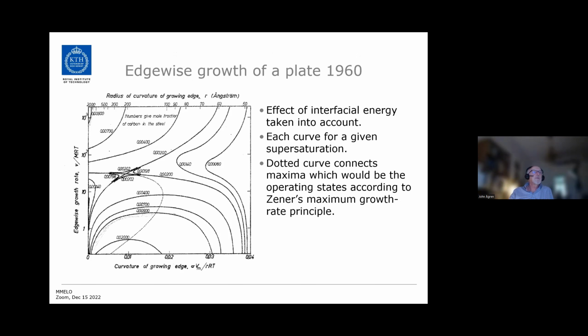So here is his results. And on this axis, we have the curvature. So it's the inverted radius of curvature. And here we have the velocity of the edge. And each curve here is for a certain supersaturation. And at very flat interfaces, and you start to sharpen the interface or the edge, then it goes faster due to the diffusion effect. But at some point, the effect of the curved interface and interfacial energy sets in, and the rate goes down again.